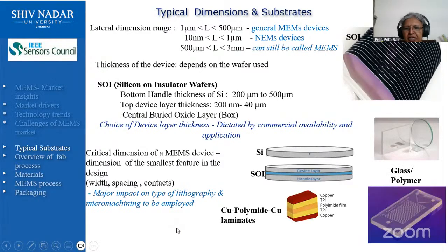Now, let me give you a glimpse of the flexible substrates. I was telling you that you do get to buy them in markets in Madras and all. It's basically a copper laminate onto a polyimide film. So there's a glue there, because when you laminate it, the copper will peel off very easily from the polyimide if it's heated up, right? So you have a heat resistant glue in between, and that's a trade secret for each company, right?